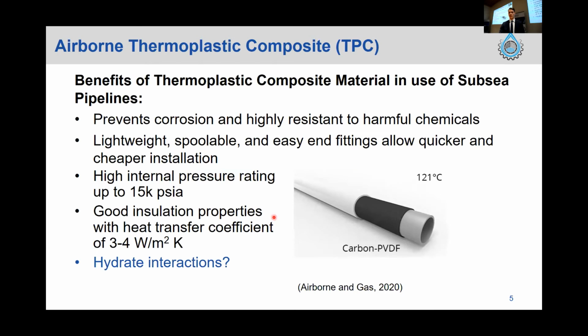The material I've looked at, which Bruce briefly mentioned, is a thermoplastic composite developed by Airborne Oil and Gas. The one I'm looking at in particular is a PVDF material, which is produced by melt fusing layers of this plastic together to form the structural integrity. Some of the properties that have been tested are a temperature tolerance of 121 degrees Celsius and a pressure tolerance of up to 15,000 PSI. One of the inherent benefits of this material is that it is corrosion resistant and highly resistant to harmful chemicals.